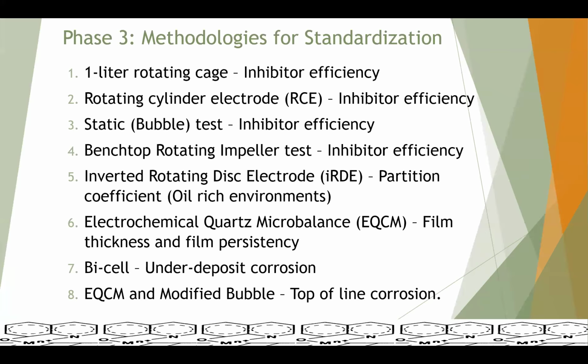In phase 3, we have identified 8 methodologies that will be standardized, of which for the first 4 methodologies, we have some kind of apparatus commercially available, but they are not standardized. Some form of methodology is available, for example, rotating cage, rotating cylinder electrode, bubble test, and the benchtop rotating impeller test. So the first part of phase 3 is to establish standards on these 4 methodologies. And for the last 4, there is a little bit of development that will be done as a part of the JIP and then standardized.